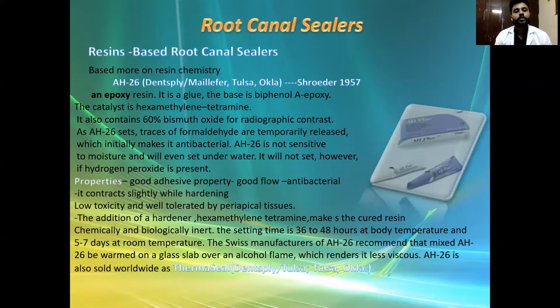Okay, so next we move on to AH26. AH26 is a resin-based sealer. So far, we have seen zinc oxide eugenol based sealers and calcium hydroxide based sealers. Now we come to AH26, which is an epoxy resin based sealer. It's a glue; the base is bisphenol A epoxy resin. The catalyst is hexamethylene tetramine. It contains 60% bismuth oxide for radiographic contrast. As AH26 sets, traces of formaldehyde are temporarily released, which initially makes it antibacterial.